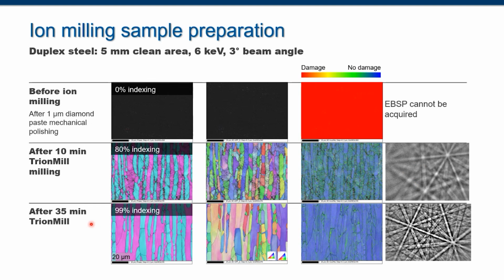But if you finish your sample preparation using a TrionMill, you will get 90%, 99% of indexing, beautiful maps, beautiful patterns, quality. If you get some local misorientation, that will reflect your native material deformation, which is real for your material, not only the surface deformation, which is easier to distinguish when you look at the results and you see the surface damage from mechanical polishing and the real material deformation.